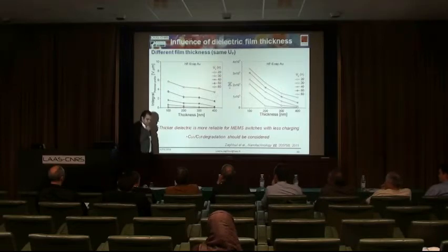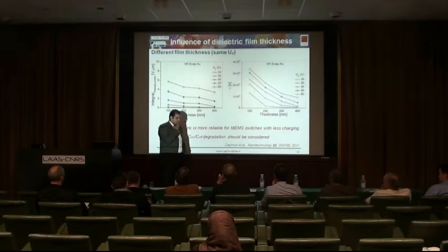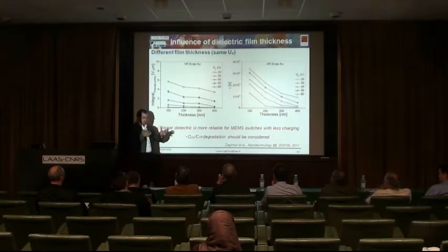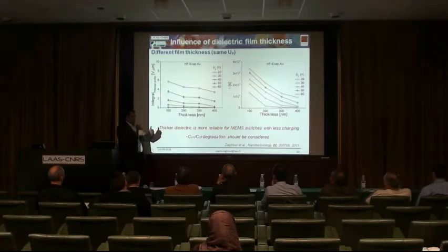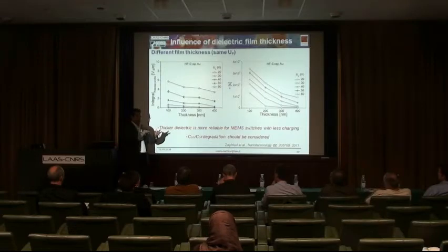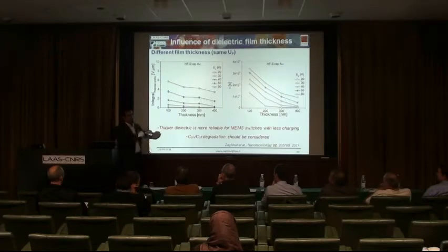Actually what we did in the beginning, in the JMM data, what we have seen is exactly what we were telling: if you have a thicker dielectric, you have a longer decay time constant. And we believed that this is because of the probability of a random walking particle, which is moving randomly till it reaches this one. So logically it was expected for 500 nanometers to take longer time to reach it. But the problem with these measurements we did in JMM is that it was at the same bias. Then we said, okay, fine, we agree now, it is following this random walking probability.